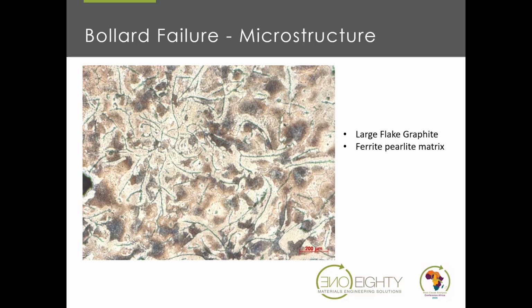Yeah, we cut things in half, we grind them, polish them, and treat them with chemicals, and we can see the microstructure. And what we see here, these squiggly lines, is called a flake graphite cast iron. The flakes are relatively large. Typically, we would consider that to be a problem in modern day cast iron making. And they are embedded in a matrix of ferrite and pearlite, which is completely normal. So the flakes are a bit of a red flag, not too much of a red flag, but a slight red flag. Not so great, but also not so bad.